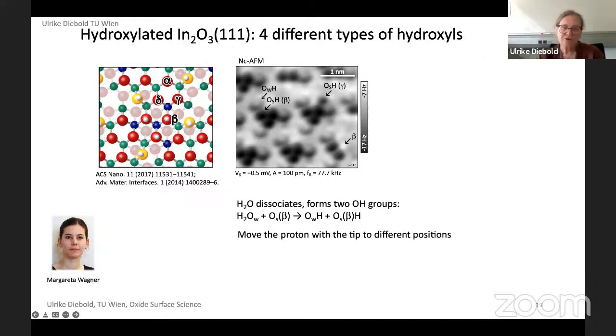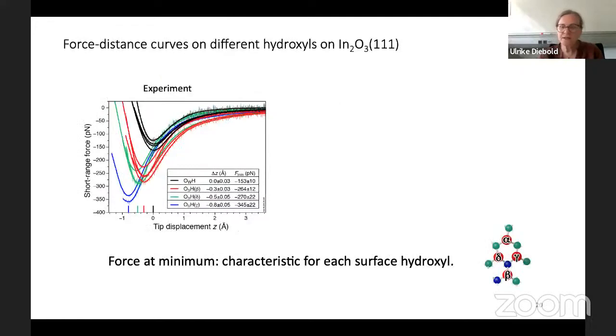And then the nice thing, I mean, this is a very delicate method, but maybe not me, Margareta can take these protons and move them from one place to another. So here there are already 3 hydroxyls in this image: one with the surface water hydroxyl, the proton on a beta surface oxygen, and then a gamma surface oxygen, by moving things around. And then one can do these force distance curves. So you park, you identify which kind of hydroxyls you have, you move the proton from one to the other, identify it, sit on one of them, and then go in and out and do force distance curves.